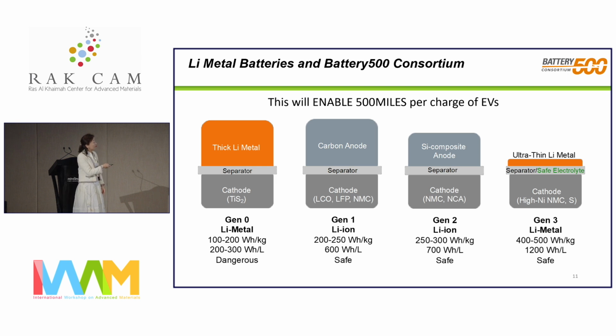Because now you have very high lithium-containing cathode materials, we should be able to just use a very thin seed layer of lithium metal, and then we can actually cycle the batteries. And just by eyeballing, you can see the volumetric energy density improvement. And this is easy said and difficult to do. Why?